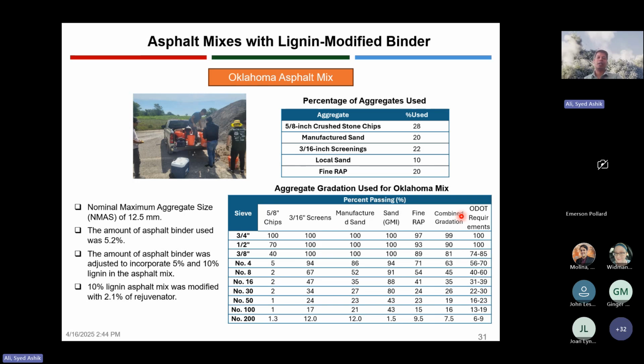Similarly, at the University of Oklahoma, we also selected an asphalt mix that had been used before, and it had a nominal maximum aggregate size of 12.5 millimeter. The amount of asphalt binder we used was 5.2%, and these are the aggregates that we used. Again, this mix also had around 20% RAP in it.